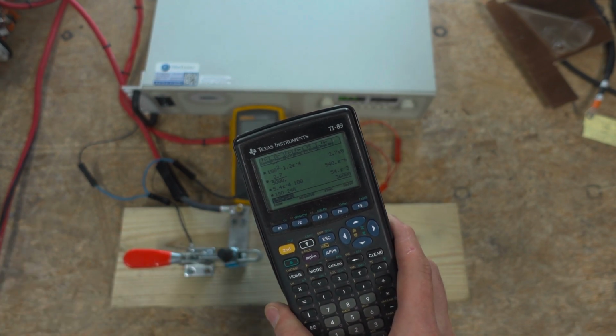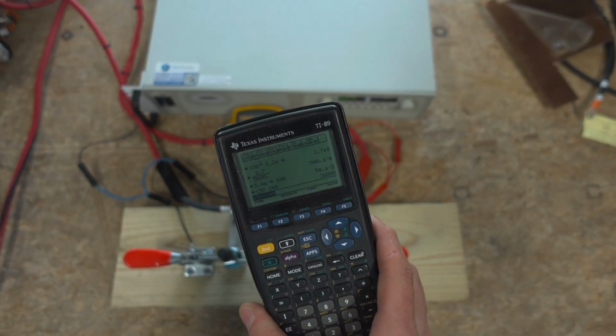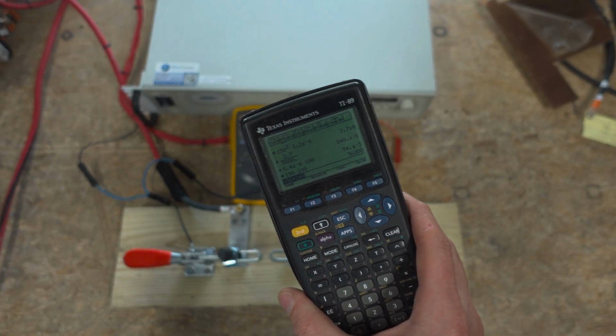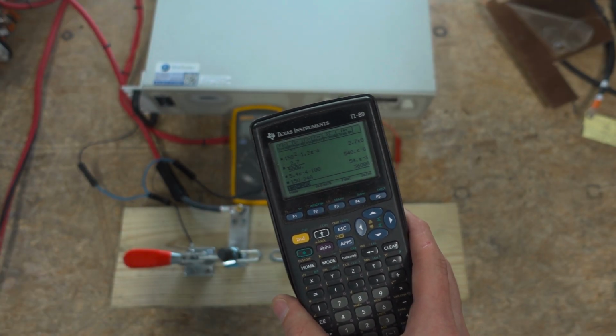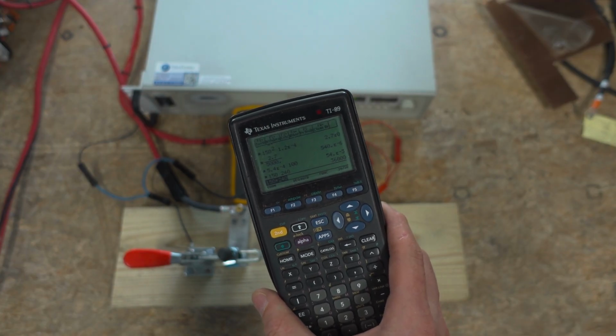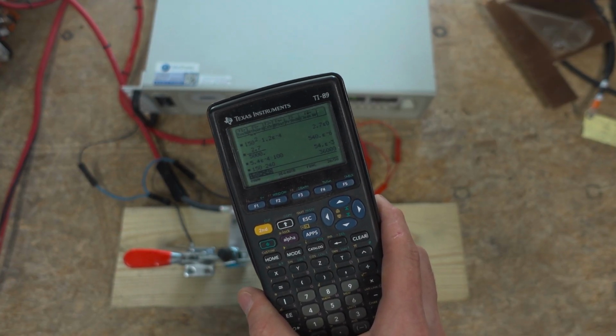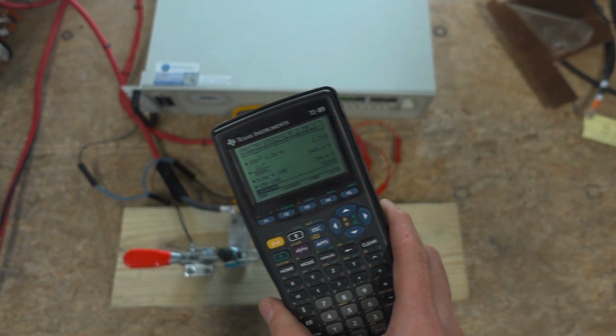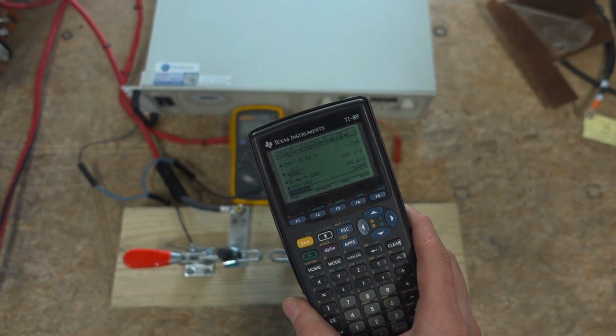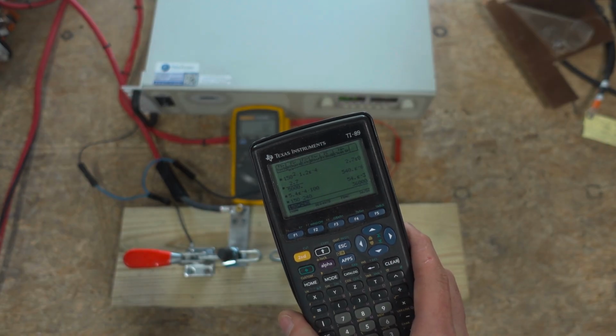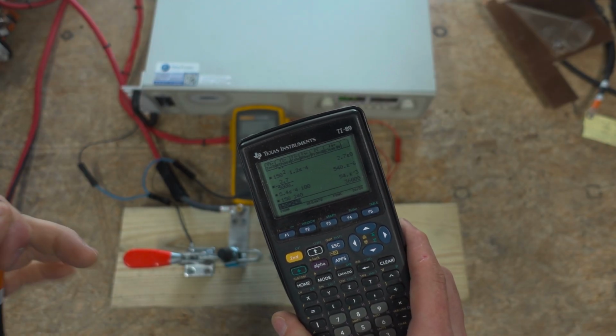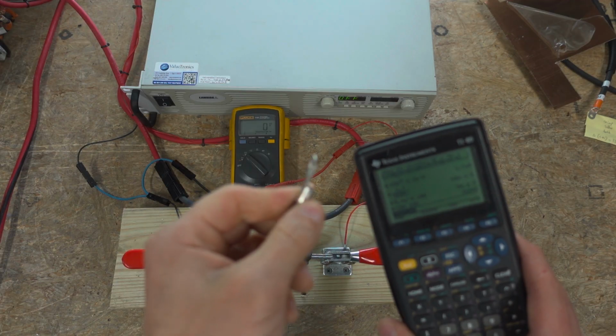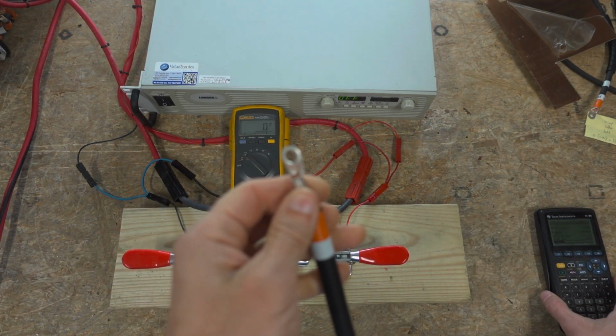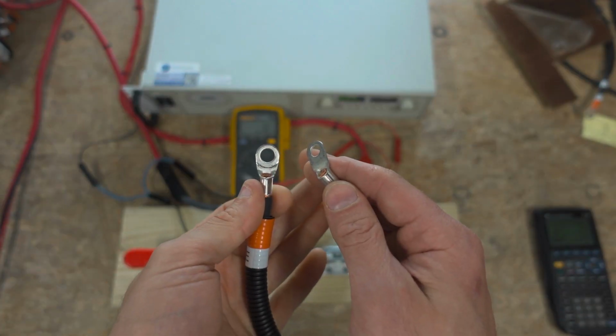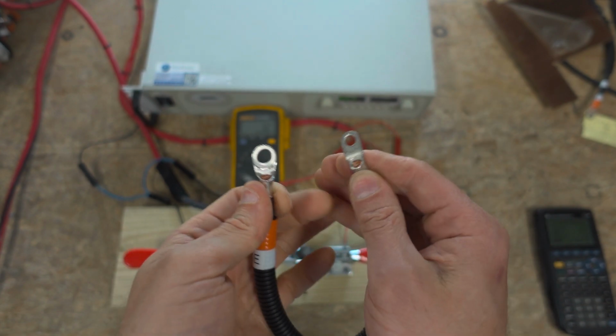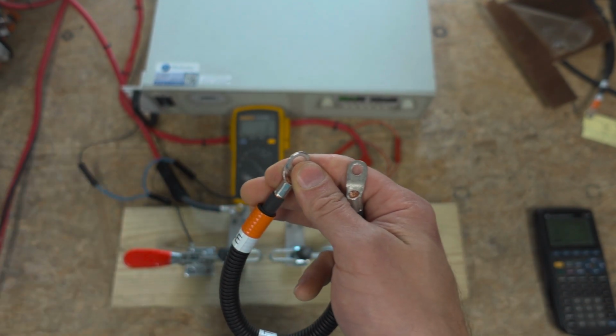So, for example, most sodium cells have much higher, in fact, I think all sodium cells have higher resistance than traction batteries used in lithium hybrids. Certainly in my testing of the sodium cells that I have tested, it's much higher. You're talking about 5 kilowatts or more of internal heat inside of the battery pack. So if you're worried about a 2.7 watt increase on something that you have maybe 10 of, you might have 10 of these connections in a pack to hook up the submodules or whatever. In some cases you might have 4 or 6.